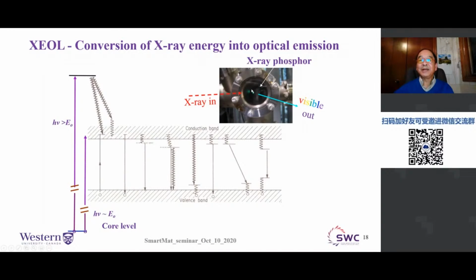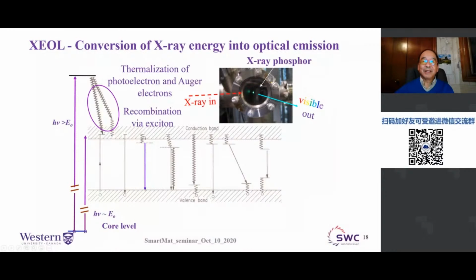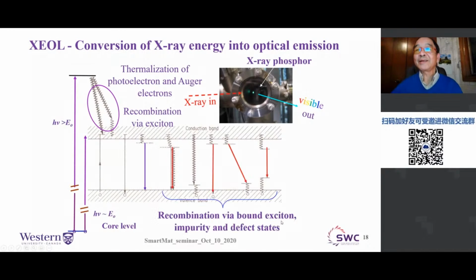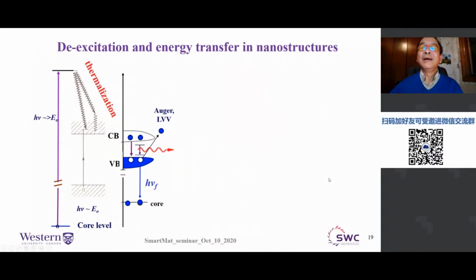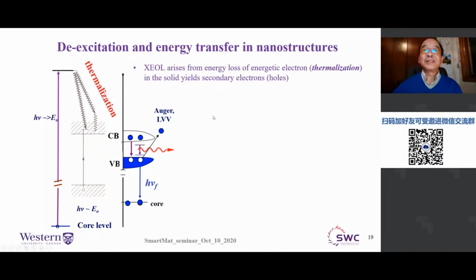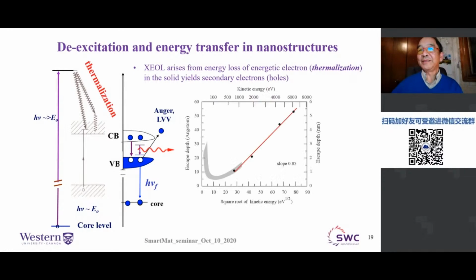Okay. Now here, if I put a phosphor in here, excited with X-ray, then I get a visible photon, right? And the mechanism is somewhat complex. The reason this comes out is mainly due to thermalization of the photoelectrons and Auger electrons produced, right? And then they can combine with exciton formation, or they can come out as defects, right? But this gives us a lot of information about nanostructures, okay? So in nanostructures, it's very important because XEOL arises from energy loss of the energetic electrons, or thermalization. Now, thermalization has a path. So for an electron to totally thermalize, if it's in a big solid, it can do that. But in a nanostructure, the thermalization is truncated.